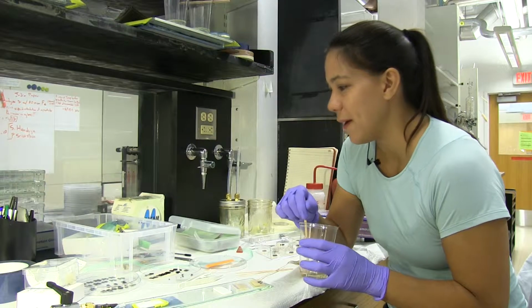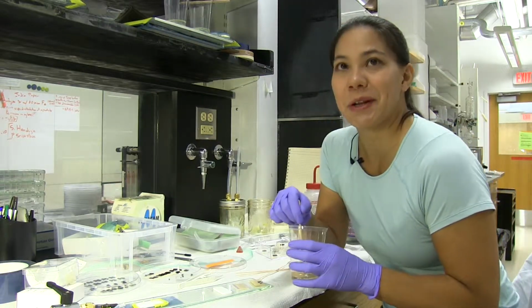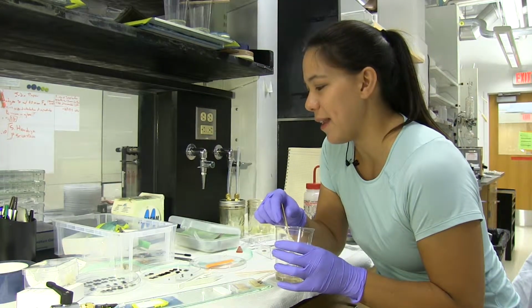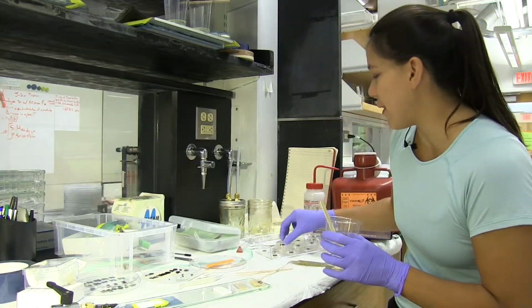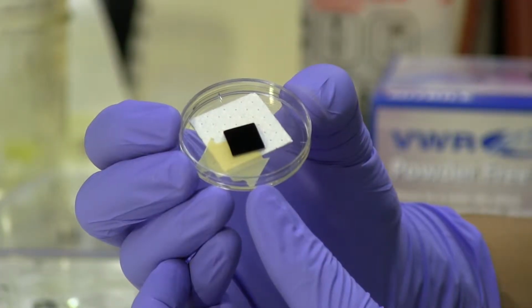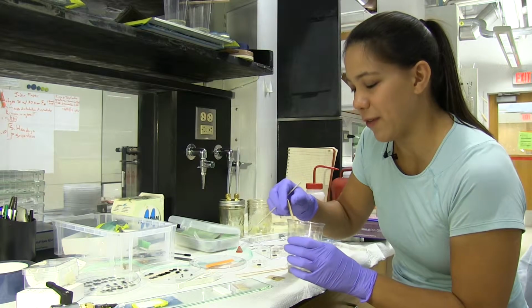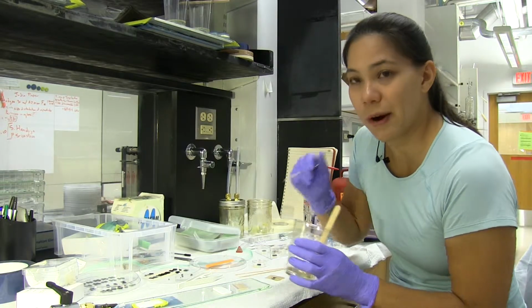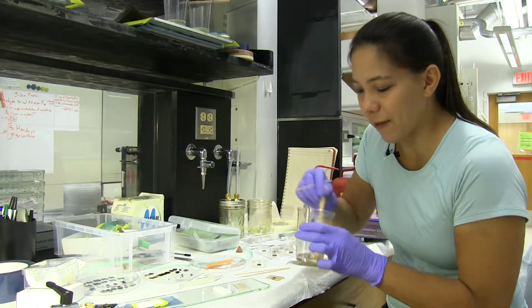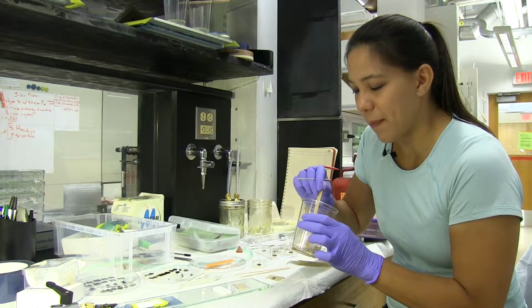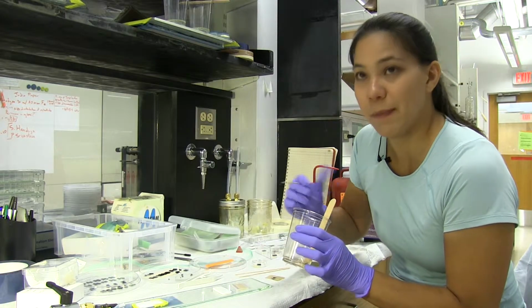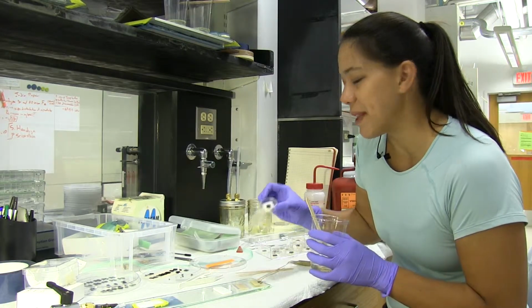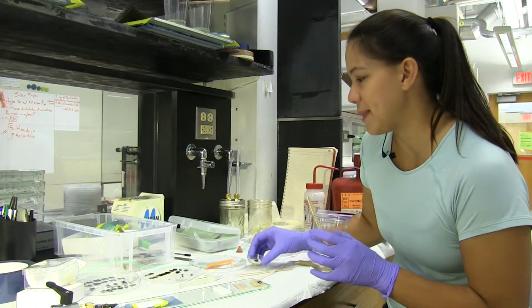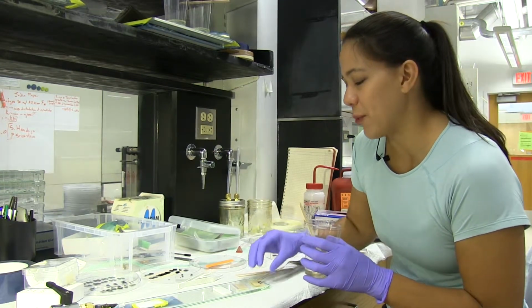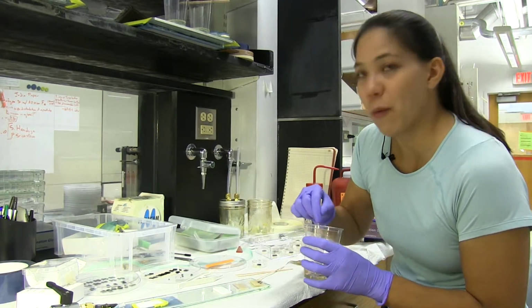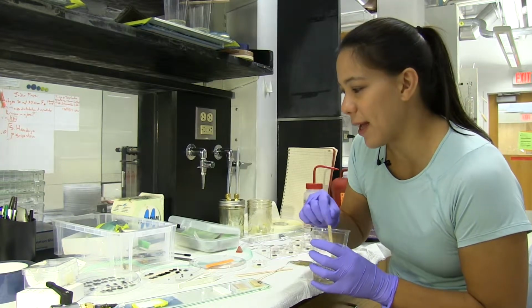I'm trying to make PNCs, so polymer nanocomposites, which is aligned carbon nanotubes, which start out as these black squares. I mixed up a batch of marine epoxy, so this is 2-part, pretty viscous. It's kind of like a warm honey. This epoxy is used for boat building, and I'm infiltrating them with epoxy to create small nanocomposites. Working on figuring out ways to infiltrate them without causing them to collapse.